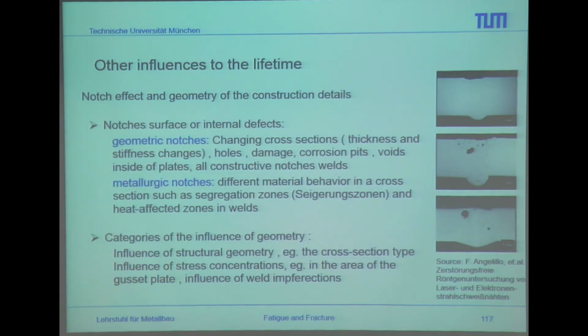So, which are the influences which have to be handled in the notch details? This is the detail which is recommended in the codes, and therefore usually you have some information due to the quality and due to the procedure, how you're going to build your welding, for example. And so this also influences your lifetime. Some effects you can see here are, for example, surface and internal defects. Surface defects would be like this, some changes in the cross section due to too high temperatures in the welding procedure. Then some inclusions, which are here in the weld seam, and all this information is at the end conducted into some categories of the weld quality.